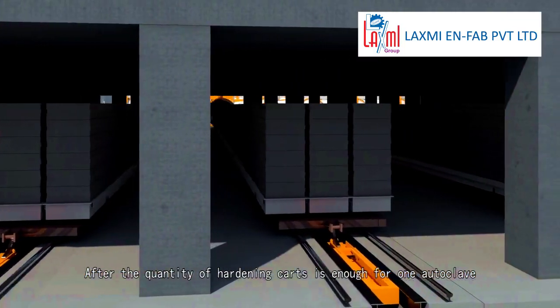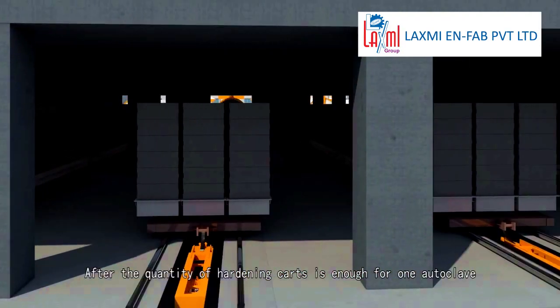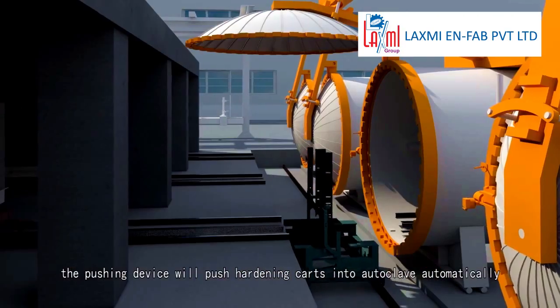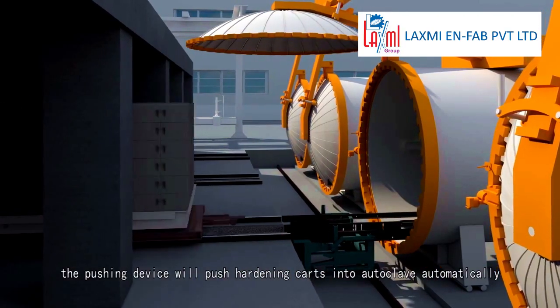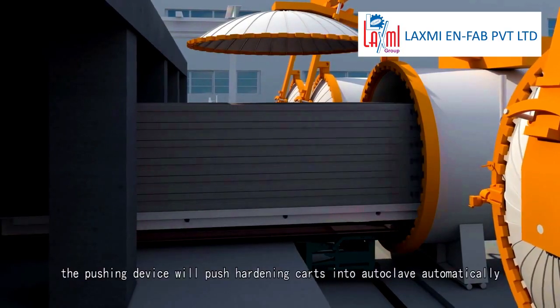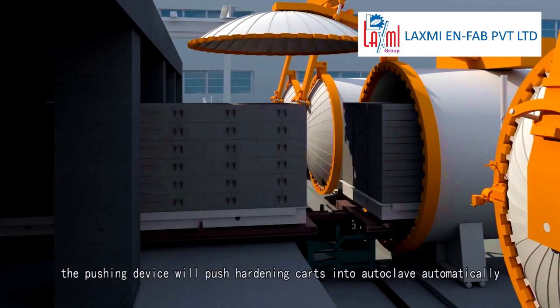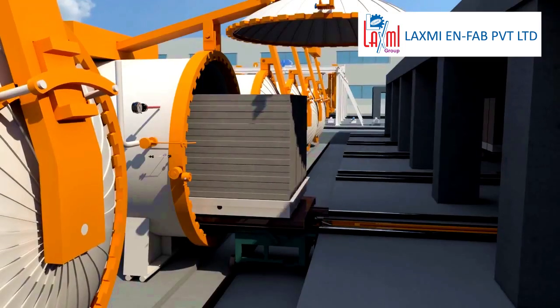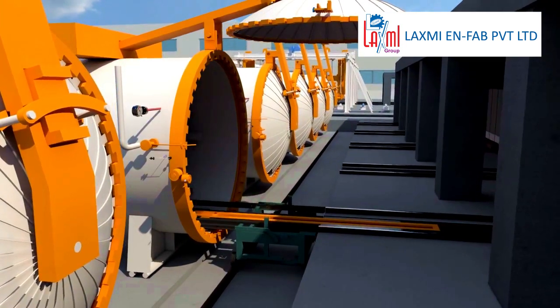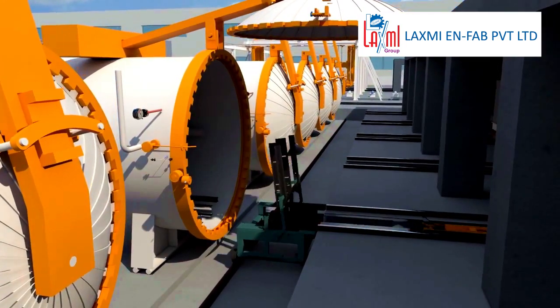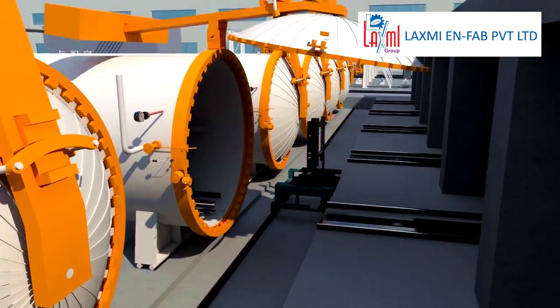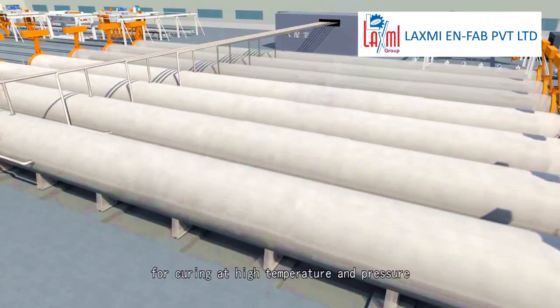After the quantity of hardening carts is enough for one autoclave, the pushing device will push hardening carts into autoclave automatically. And then, the cakes will stay in autoclave about 8 to 11 hours for curing at high temperature and pressure.